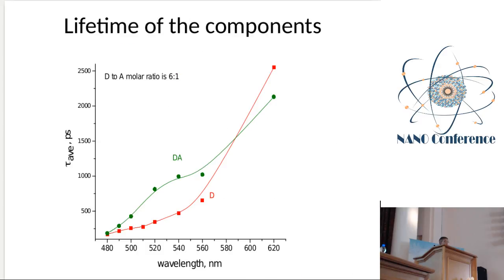So, if we look into the other components of emission of the donor aggregates in the presence of the acceptor, we can see quite a big difference. The lifetime of many components not only changed but even increased. That means that energy transfer is significantly delayed in this process, in the solution.